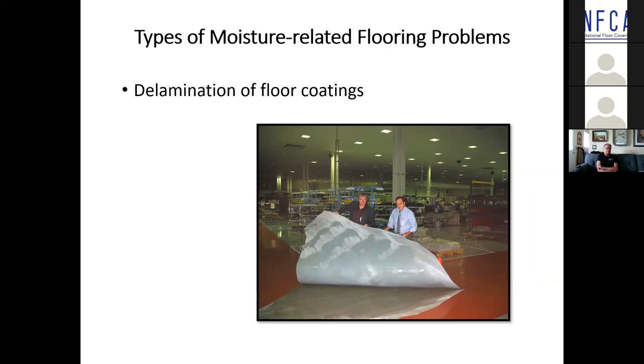And as they moved across, the epoxy mitigation system went down, and then a high build static dissipative epoxy went down. Well, by the time they were about 90,000 square feet across the floor shot blasting, and the first area was done, the owner or the operator of the facility was in there snapping chalk lines and getting ready to set up equipment and so forth, but brought the contractor over and said, by the way, what are all these bubbles? Time out, stop the process, start the investigation. But there wasn't time to do a proper forensic investigation.